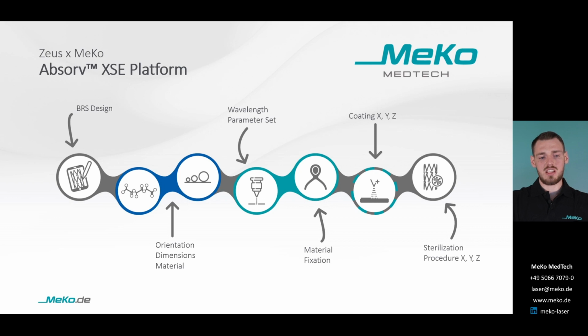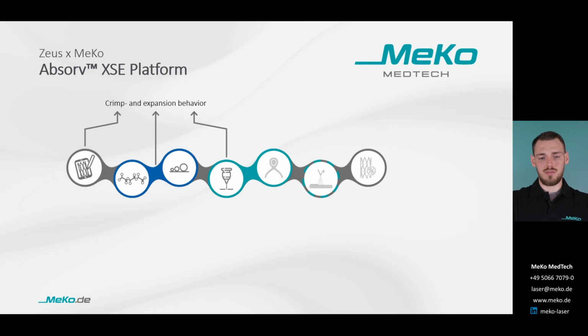The crimp and expansion behavior, for example, is of course a very important feature for the BRS, and this is tremendously determined by the design itself, which needs to match perfectly with the material used. Zeus' capability to trigger the molecular orientation really brings advantage here and has the potential to take the BRS to the next level. However, the theoretically best design is useless if it is not realized with the required precision.